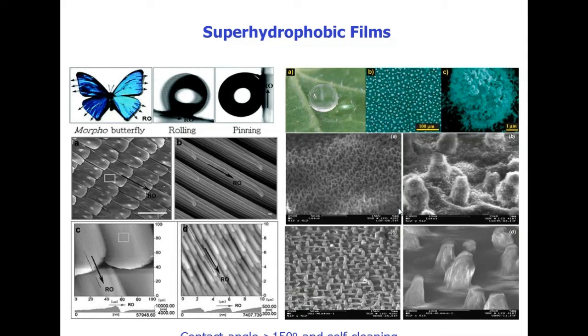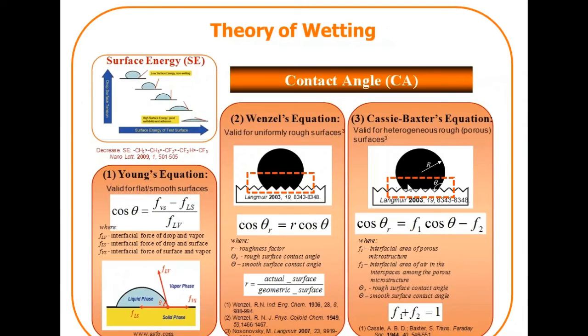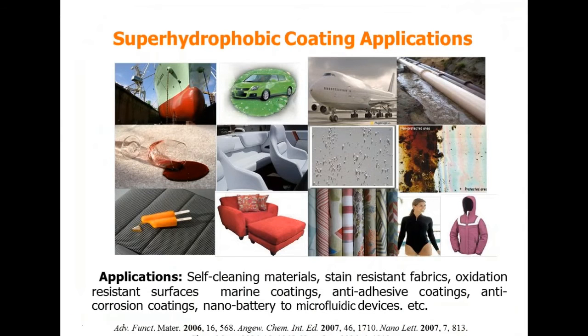This is explained by the Cassie-Baxter approach, which involves de-wetting entry and re-entry phases of a droplet of liquid, essentially trapping air inside hierarchical infrastructures that results in non-contact wetting. And hence you get the superhydrophobic effect. A superhydrophobic effect can be quantified and produced artificially as well. So what are the uses of a superhydrophobic coating? Superhydrophobic coatings allow us to produce fouling resistant surfaces, whether on paint, textile, different types of appliances, pipelines, or even controlling flow assurance in terms of transport of liquids.